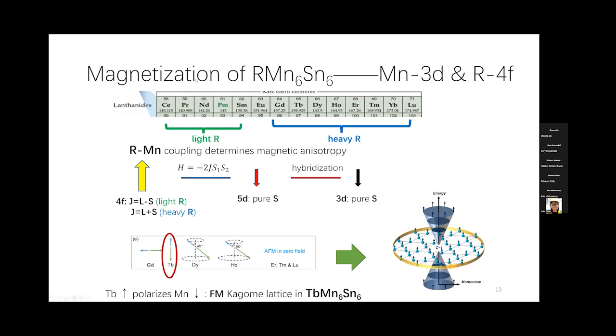So before I discuss some transport properties, let's examine the magnetization for rare earth manganese 6 tin 6 at first. Basically, the magnetic structure is determined by the strong coupling between the rare earths and the manganese. Here, the magnetic coupling is indirect, through exchange interaction with the 5d electrons. So basically, the spin part of the rare earth atoms is anti-parallel with the direction of the 3d local moment on the manganese.